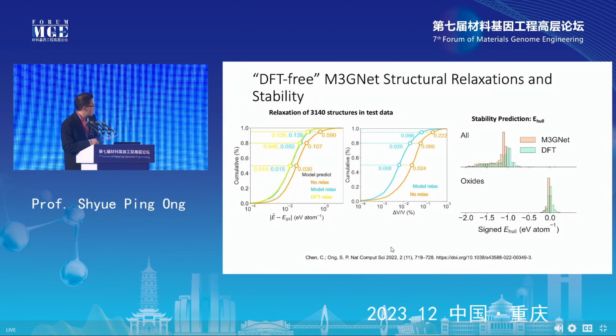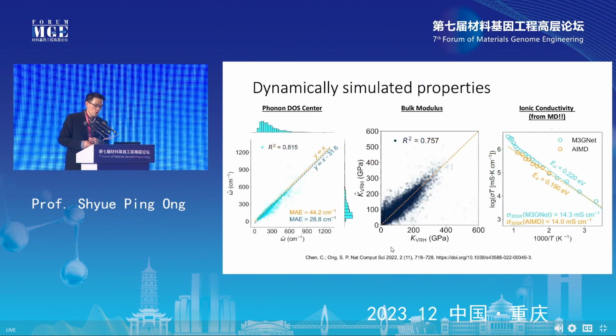Once we are actually able to get structures that are within 1 to 2%, we can also calculate its energy and make stability predictions, right? And we can show that basically our stability predictions are in very good agreement with what you would get from DFT calculations, right? You can also get a lot of different properties from a universal potential.